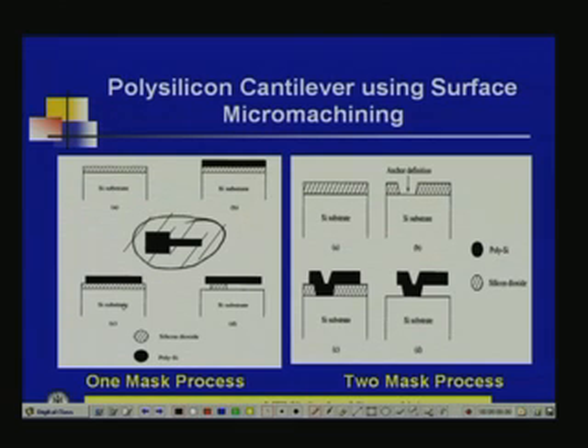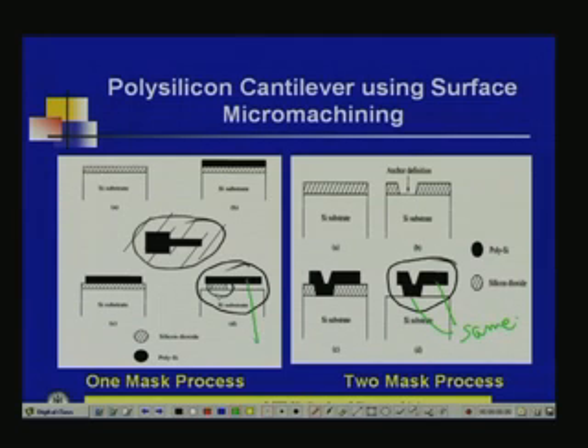I mentioned some limitation. What is the limitation? The limitation is that the beam is floating here, supported on silicon dioxide, but if you go for the two mask process, this region is also made of the structural material. Just see it side by side. Here the first mask is the anchor definition in the structural layer, then you deposit polysilicon, then you remove the structural layer, and you get this structure. If you compare these, you see here this material and this material are both the same, but here this one and this one are different.